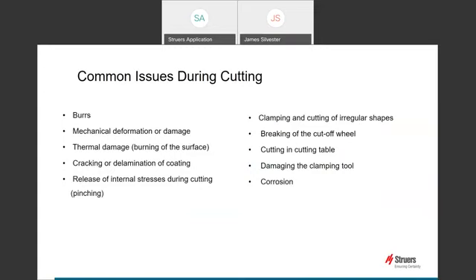The list on screen outlines some of the common issues we can encounter during cutting. Poor clamping and cutting setups can lead to many of these, either in isolation or more often at the same time. Typically, the more complex the cut, the more chance of these events occurring. So take the time to look at the sample you have clamped and work through in your mind what will happen when I make the cut. Do I have enough support once a piece is cut away, and am I cutting into a load-bearing section? Always take a moment to look at your setup before you start the cut. Once you press go, it's often too late.